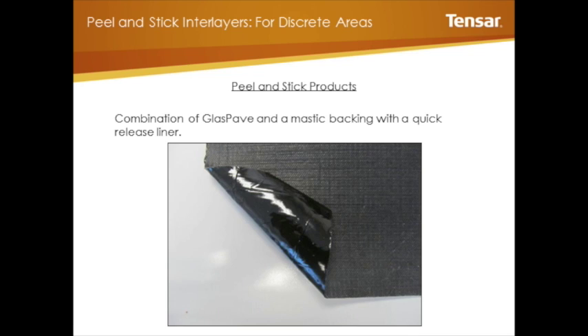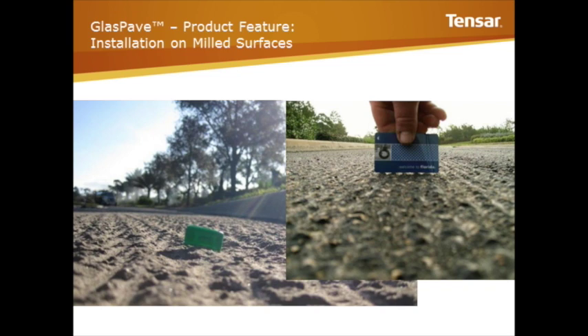The nice thing about an interlayer, you can stop and start the use of these materials without having to make it continuous. And we know that pavements deteriorate in very isolated areas. So you have severe areas and less severe, but you typically apply a standard approach, a standard overlay thickness. And you can use an interlayer within that individual design section wherever you wish to without having to change the profile thickness, which generally creates problems. So in this particular case, it lends you that convenience.